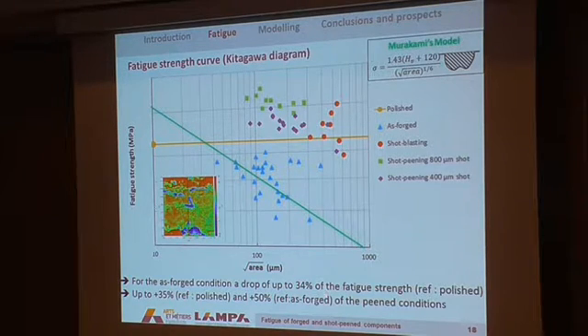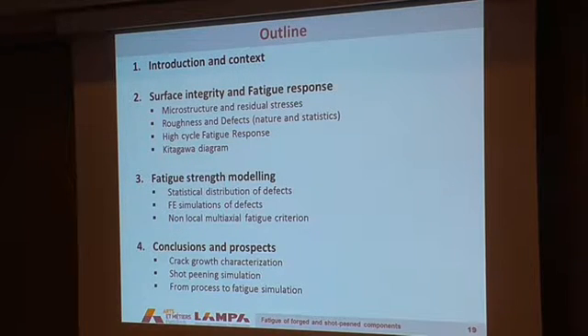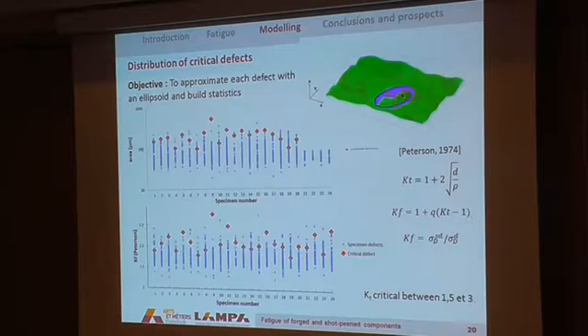And what's important here is that even for the as-forged conditions, the presence of defects induces a drop of up to 34% compared to the reference, whereas for the other conditions, we got something like a 35% increase of the fatigue strength. But what's important here is that for the biggest defect in shot blasting, you got something which is close to the polished fatigue strength. So you have to take into account the effect of the defect and, of course, the effect of the residual stresses. It's what I'm going to do now in the fatigue strength modeling part.